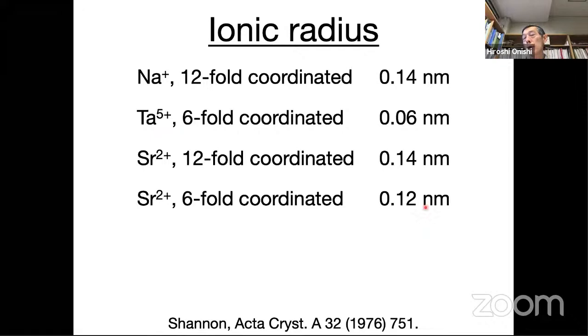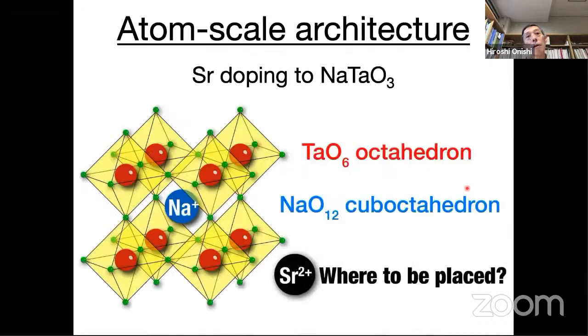So just looking at this table, we can guess strontium can replace the sodium cation because the sizes of the two cations are very similar. So it should be easy to replace one sphere with another sphere of similar radius. So researchers naively believed that strontium cations should be here, replacing sodium cations, but there was no experimental evidence at that time. So we decided to confirm, and found this was not the case. Strontium was in the sodium place and also, at the same time, simultaneously in the tantalum site. This was very surprising for us and also for the researchers in this area.